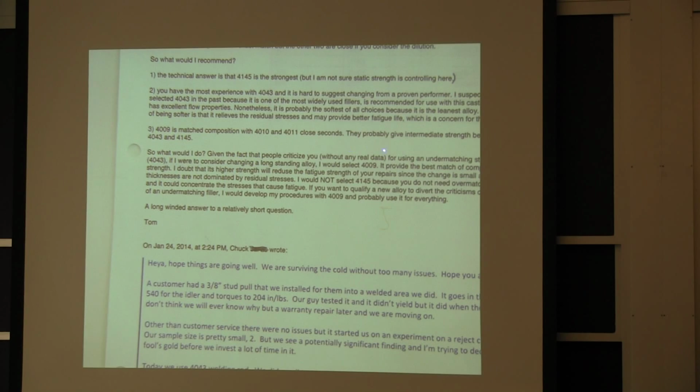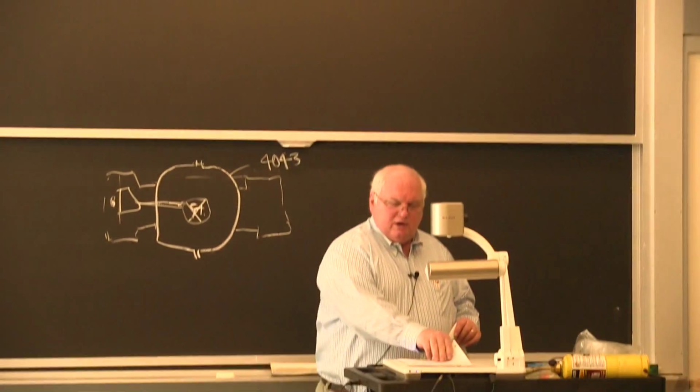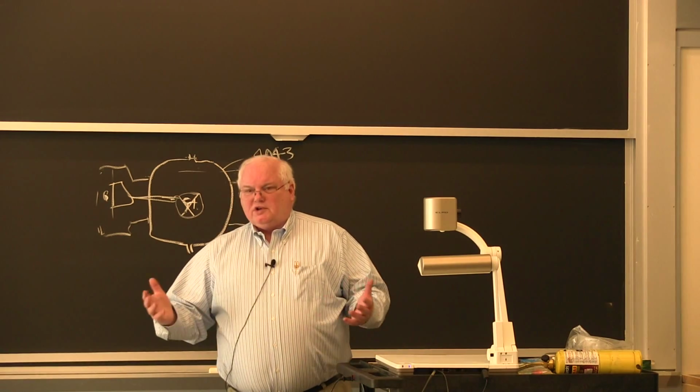So what would I do? Well, I'd either stick with what you've got, or if you want to change and get rid of this criticism, because people say, oh, you don't have the exact same composition. And that's a stupid argument. It means they don't understand welding science and stresses. But people make those arguments. If you want to come up with something matching, I wouldn't go to 4145 because it doesn't match. They're going to give you the same argument on the other side of the strength, right? They're going to say it's not the same. Go with 4009. It's permitted under the recommended materials, and it will probably work just fine.